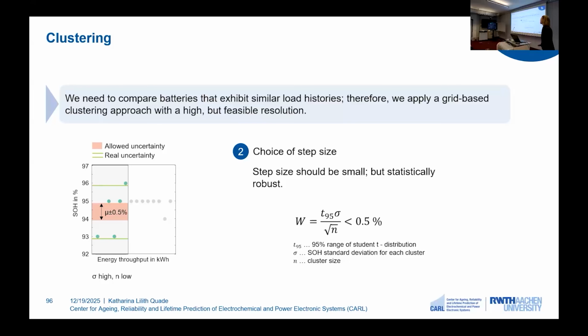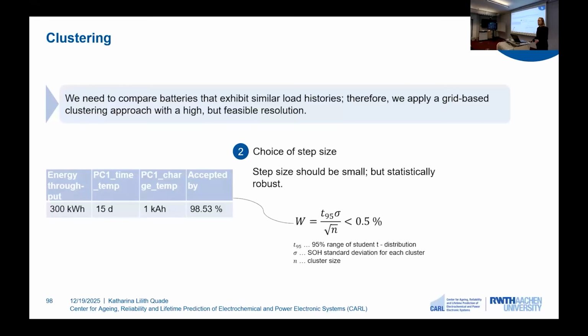So this would not be a robust cluster. However, if we now include more data points that are also closer to the mean, we get a different picture. We see that our n is higher and also our sigma is lower. This means that for us, this cluster is robust and we can use this cluster for anomaly detection. We now check for all of the different data points for how many this condition is accepted. And we can see that for a step size that is seen here, we have an acceptance rate of 99%.